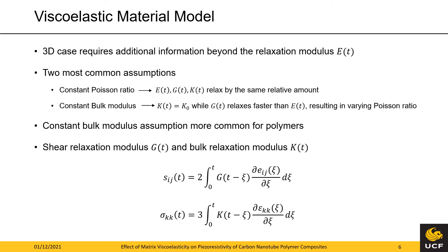The first equation links the deviatoric stress by means of a convolutional integral to the shear relaxation modulus and the deviatoric strains, whereas the second equation provides the same relationship for the hydrostatic stresses, bulk relaxation modulus, and hydrostatic strains. These equations are utilized by the finite element model and Prony series are used to represent the shear relaxation and bulk relaxation modulus respectively.